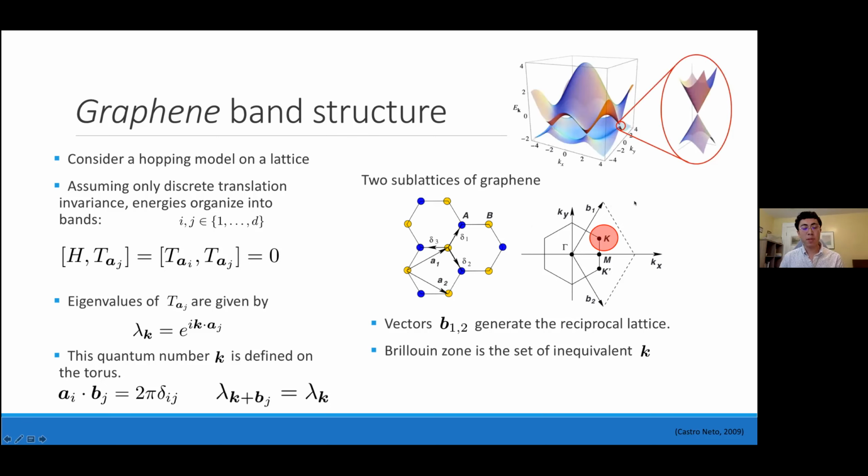Now, up until this point, we haven't said anything about the energetics of graphene. Another wonderful feature of graphene is its half electron occupancy. So if you fill at the natural occupancy at which graphene occurs, the low energy theory is described by two inequivalent Dirac points. Why do we call them Dirac points? Well, it's because their energy dispersion mimics that of relativistic Dirac particles. And so we have two of these inequivalent cones, as I'd hinted, and they're located at what we call the two valleys of monolayer graphene, K and K prime, and I've circled K there.